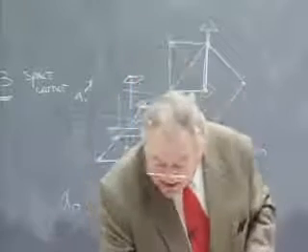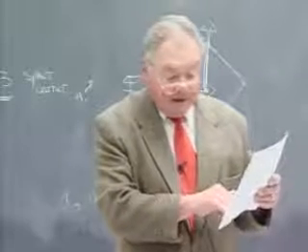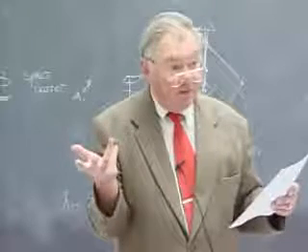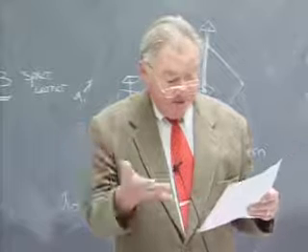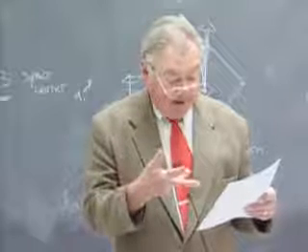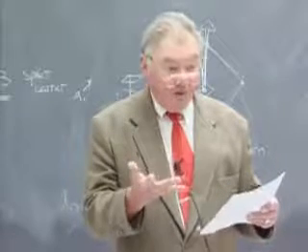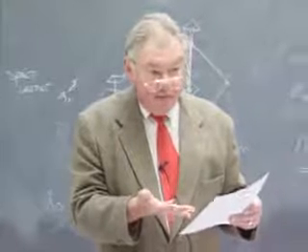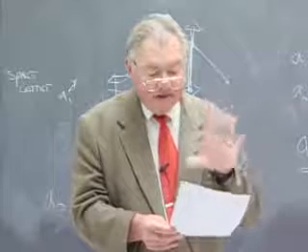So the requirements of a 6-fold axis, which gave us the primitive hexagonal lattice, are also met by 6 over m. The requirements of a 4-fold axis, which gave us the primitive tetragonal and body-centered tetragonal lattices, are also satisfied by 4 over m.